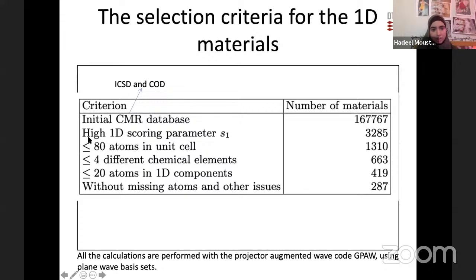And for that, we have some criteria. First of all, that the 1D scoring parameter is larger than all the other scoring parameters, both the low dimensional 2D and 3D, and also the mixed dimensionality scoring parameters, that the unit cell includes up to 80 atoms and up to 4 different chemical elements, and the 1D component includes up to 20 atoms, and we removed by hand all the materials that have some issues, be it missing atoms or invalid structures like theoretical structures or partial structures, and then we end up having 287 materials, which we will call our core materials.